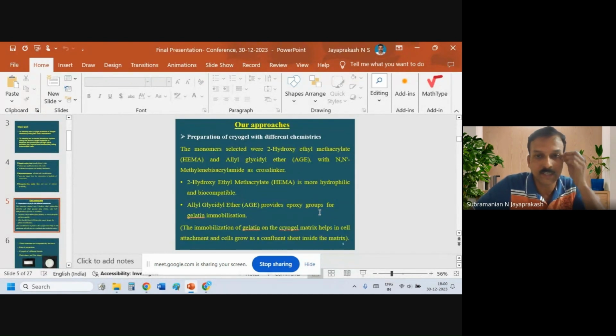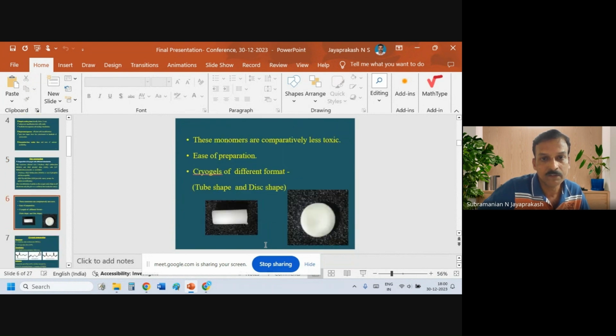So we prepared cryogel with monomers like 2-hydroxyethyl methacrylate and allyl glycidyl ether, with methylene bisacrylamide as cross-linker. And you all know that hydroxyethyl methacrylate is more hydrophilic and also biocompatible. And AGE provides epoxy groups for gelatin immobilization. The immobilization of gelatin on the cryogel matrix helps in cell attachment, and also allows cell growth as a confluent sheet inside the cryogel matrix. These monomers are comparatively less toxic and easy to prepare, and we can also make different formats of these cryogels. We can make tube-shaped cryogels as well as disc-shaped cryogels.